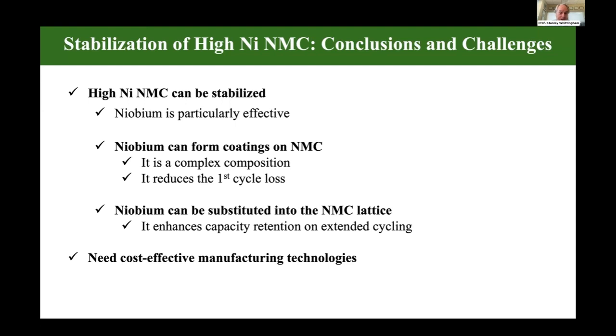It can form coatings readily on these NMCs. It's a complex composition. It reduces the first cycle loss. And we've shown that niobium can be substituted into the NMC lattice. If we go to too high a temperature, it will get pushed out of the lattice onto the surface. So it can clearly enhance the capacity retention on extended cycling.